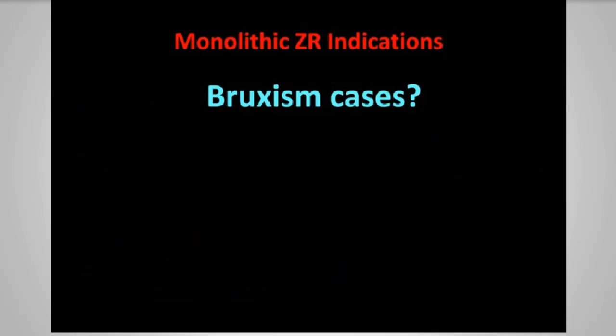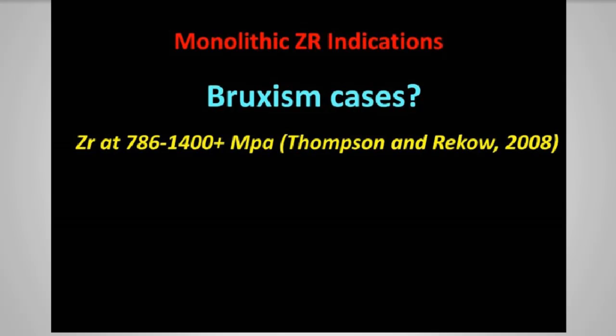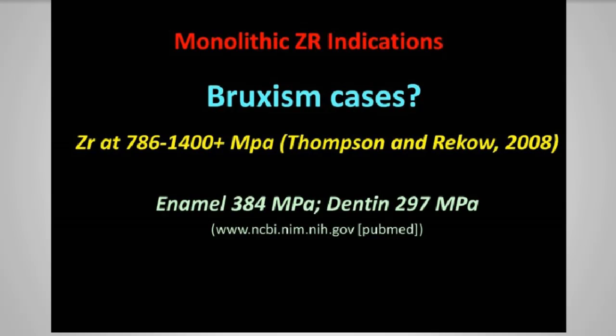What about bruxism cases? It's kind of ironic we have one of the most famous ones called BruxZir. Well, the material is extremely hard, nothing like we find in nature. How much more is it than nature? Well, look at enamel and dentin. So we have to ask ourselves, when we look back at part one, where I talked about layered porcelain being the weak link, that really is the layering porcelain over zirconia or PFMs at about an average of 120 megapascals that can fracture under load, or where it's been maybe not adjusted properly or left high in occlusion. The bottom line is, in any system, the weak link will break.